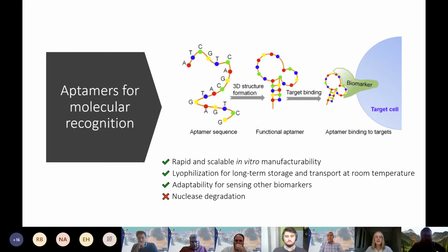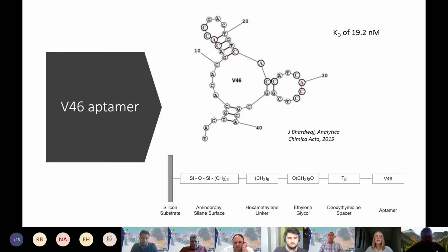To limit nuclease degradation, artificial L-DNA was used to create the Aptamers, and the heat treatment will denature any nucleases on the cartridge within 5 minutes of testing, minimizing exposure time. From this, we estimate that our Aptamers will withstand at least 8 tests before any notable loss of performance occurs. 8 cartridge uses means 8 times less waste. The V46 Aptamer, selected for its high affinity towards both the HA stem as well as the whole H1N1 virus, forms the molecular recognition element of our biosensor.